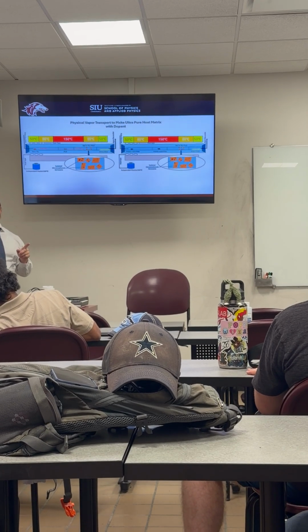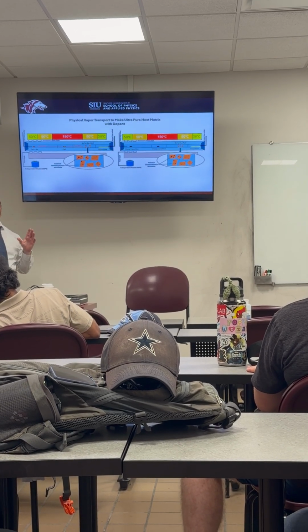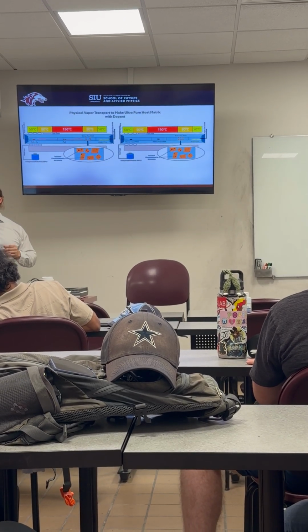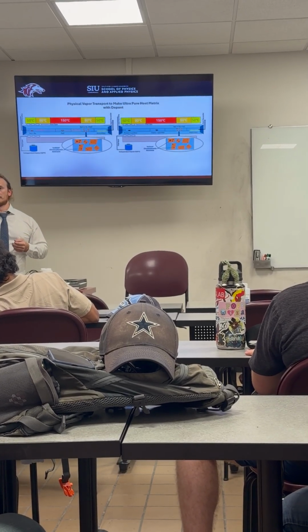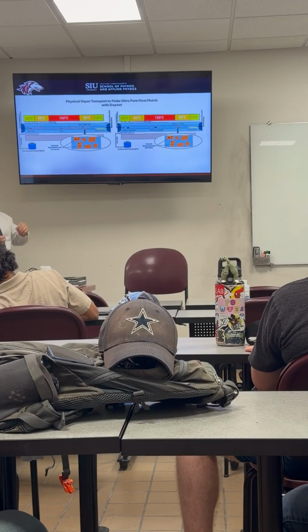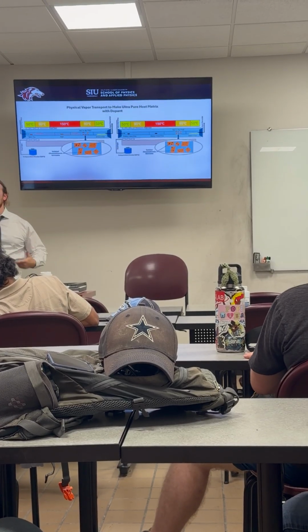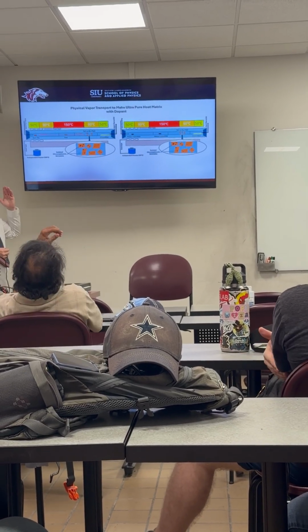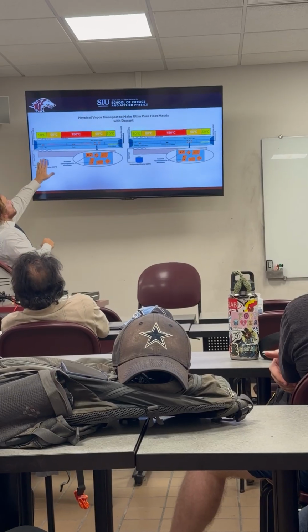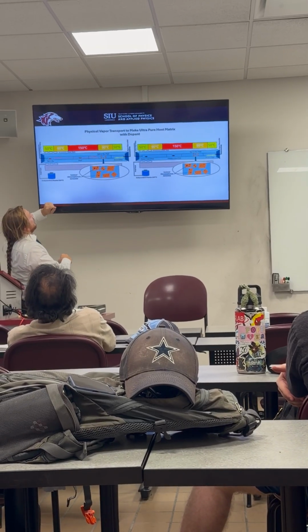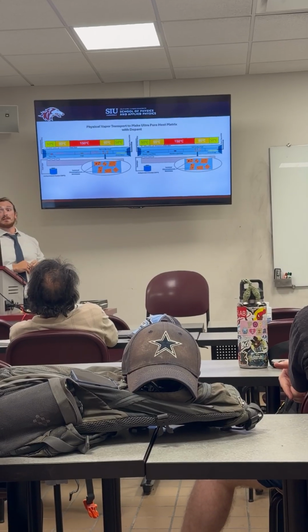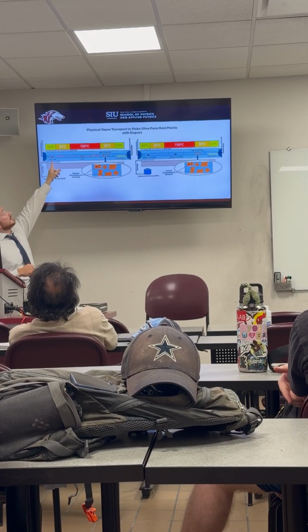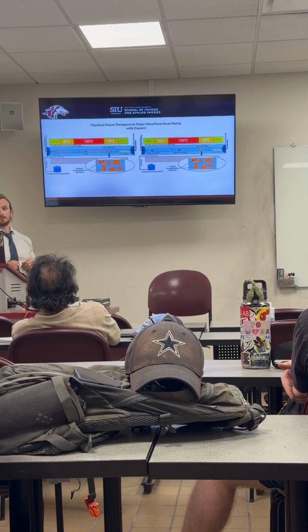Remember, as I said a while ago, the sublimation temperature of each material or compound is different. The chromophores are very stable and resilient compared to the ferrocene or cobaltocene and nickelocene. So, just to run through the scenarios here, if I did not have this independent heater, I would grow ferrocene crystals, but the temperature is too low to deposit any tetracene or rubrene inside these crystals.